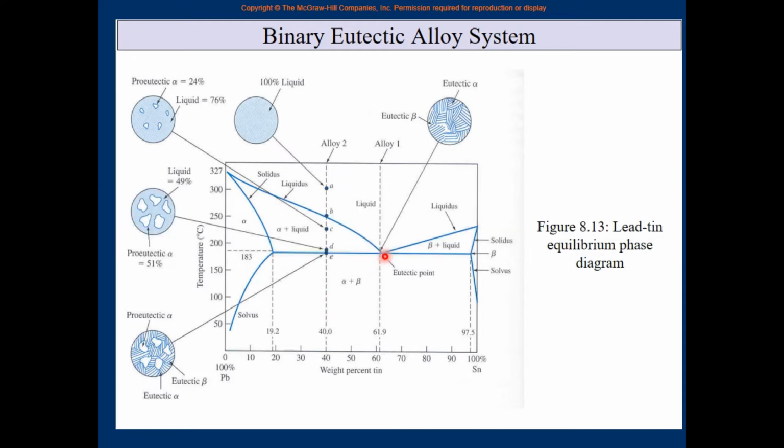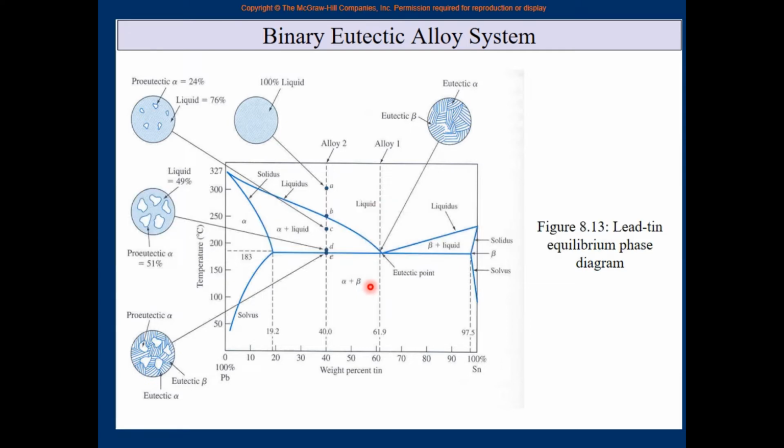This point is very strange. Just shift this dashed line to exactly this point. Here it is liquid, liquid, liquid. No liquid plus solid happens. It suddenly changes to complete solid. So this is the unique point. It was not there in any of the previous diagrams. We had the copper-nickel diagram, the silver-lead diagram, silver-palladium. It was not there. Liquid always becomes liquid plus solid and then becomes solid. Here, at one point, liquid directly changes into two solids.